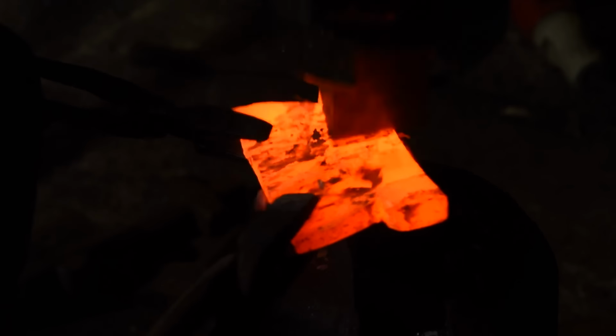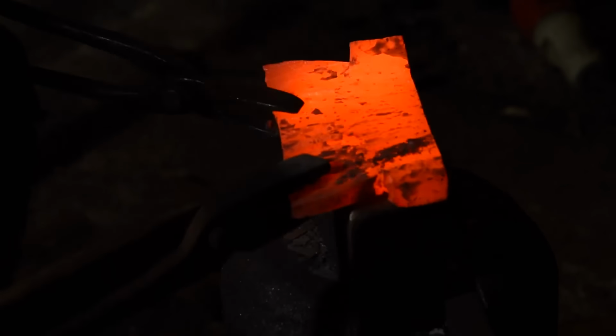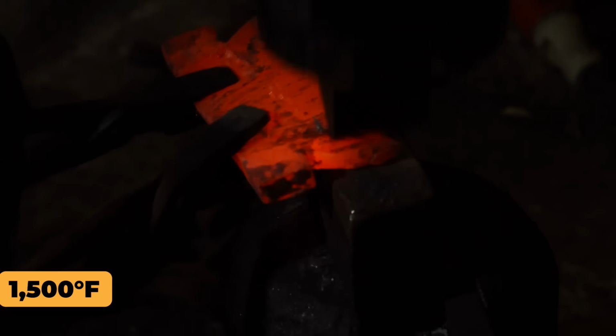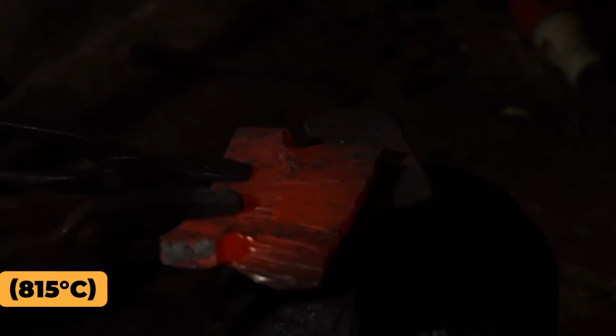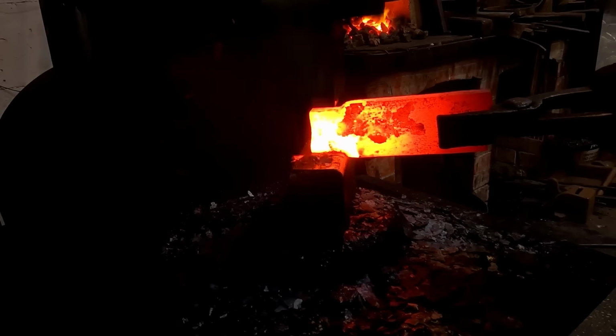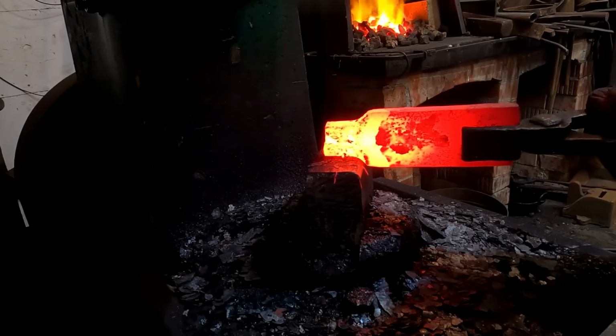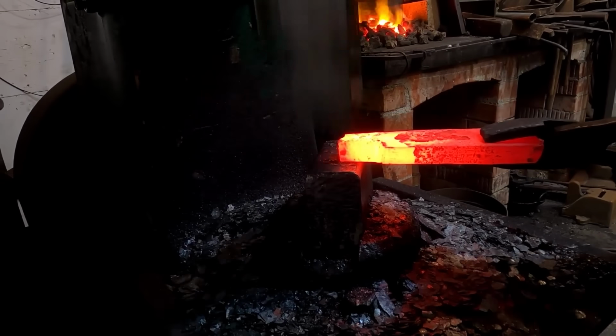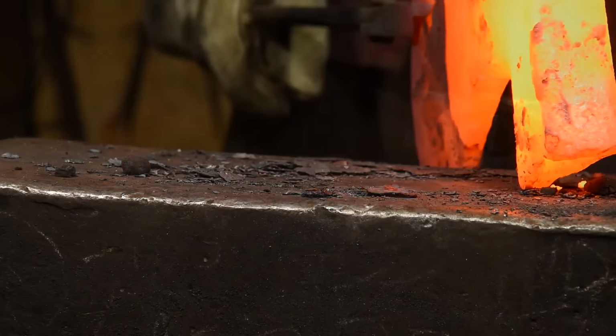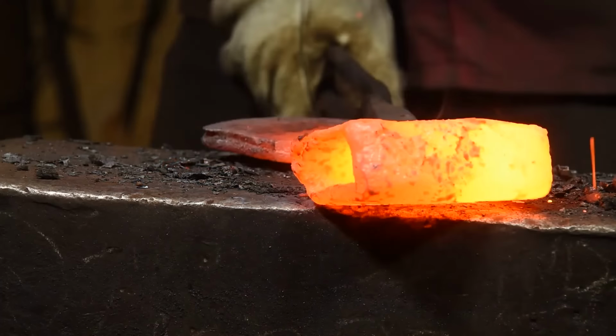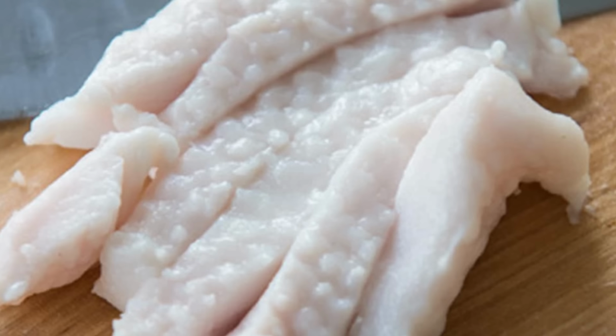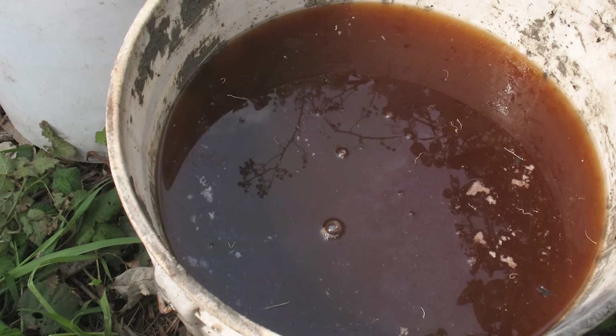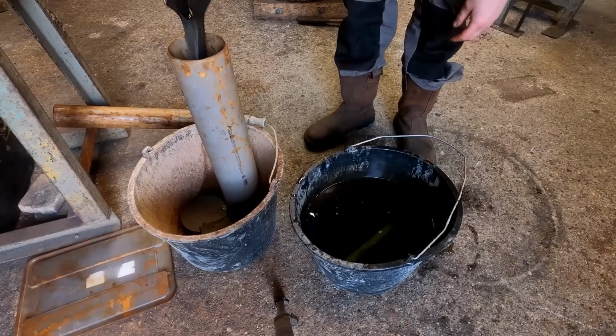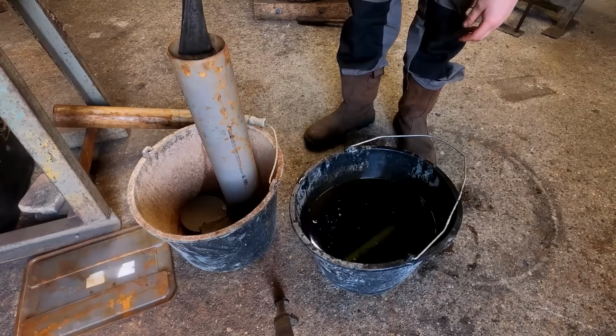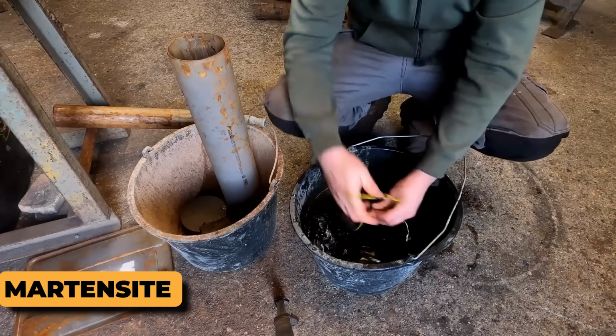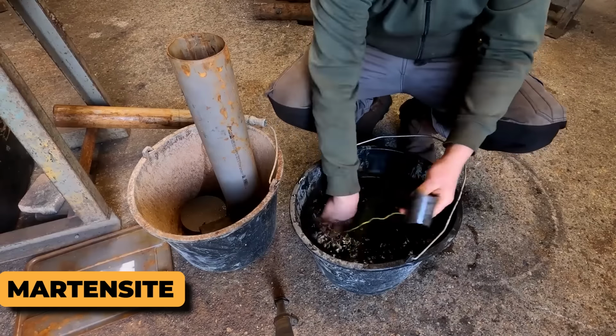They reheated the blade again, this time aiming for a cherry red glow around 1,500 degrees Fahrenheit, 815 degrees Celsius. You couldn't use a thermometer, so you judged by color. Too cool, and the edge would be dull forever. Too hot, and the blade warped or cracked. When the temperature was perfect, they yanked it from the coals and plunged it into a vat of animal fat or stale urine. Yes, really. Quenching wasn't just dramatic, it was essential. The sudden cooling realigned the iron crystals into martensite, a microstructure harder than anything the Vikings had seen.